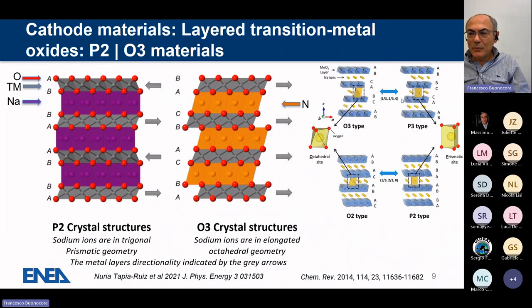During the variation of the sodium fraction intercalated in the oxide, the phase can change. Of the two phase transitions we see here, from P3 to O3 and from P2 to O2, we prefer the P2 to O2 transition because it allows the lattice not to distort. The problem in the P3 to O3 transition is that it requires distorting the crystal. This results in damage to the cathode material, so you cannot do several cycles of charge-discharge. So we prefer the P2 phase. The challenge of our research is to find the crystal with the most stable P2 phase.